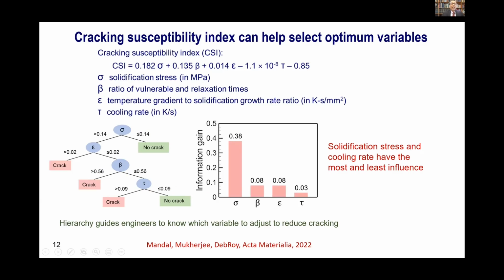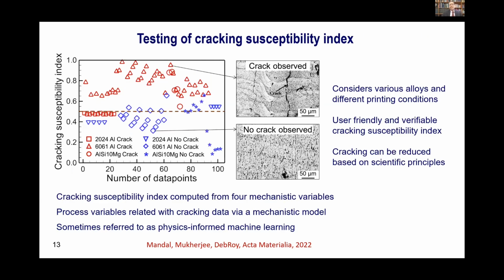We developed a cracking susceptibility index that was just published last month in Acta Materialia, and we found that solidification stress is the most important variable for controlling cracking in metallic parts in aluminum alloys. And the least important factor was the cooling rate. Engineers can use these to control cracking, but how do I know that the cracking susceptibility index that we developed based on data science actually works? So I'm showing you how we validate it.